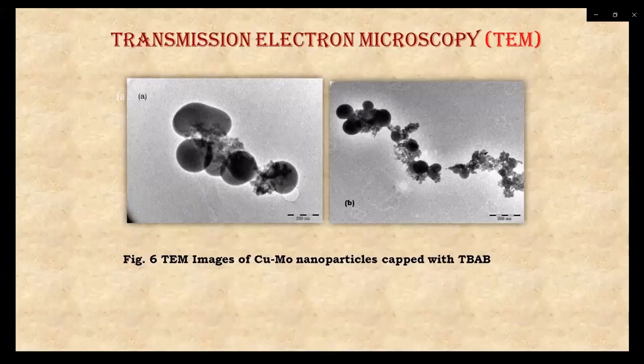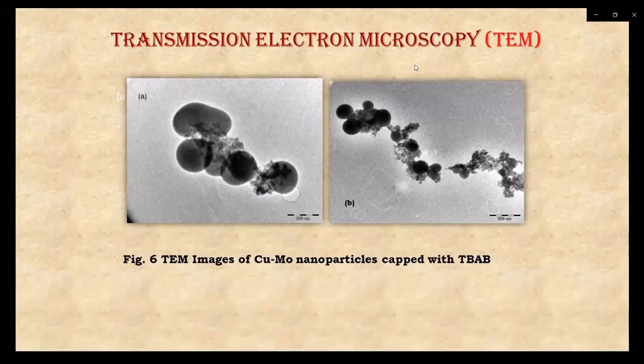To know the exact morphology of bimetallic nanoparticles, we characterize it again by transmission electron microscope. The TEM images show monodispersed copper molybdenum nanoparticles, spherical in shape, with 5 to 10 nanometer average particle size.